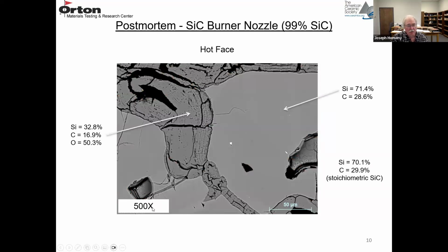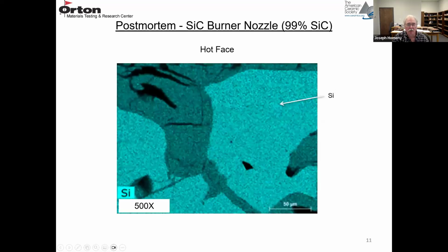And this is just a higher magnification. So here's a silicon carbide crystal intact. It's about 71% silicon and 28, 29% carbon. And this is stoichiometric silicon carbide, about 70% silicon and about 30% carbon. So this is unaffected, but the area between the crystals is oxidized. So you can see the silicon content's about 32%, carbon's about 17, and then there's a lot of oxygen present. Half of it is oxygen, 50%. So that's the portion that's been oxidized.